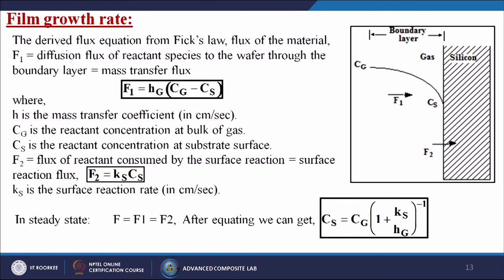So, the famous equation, calling it Fick's law, is F1 equal to Hg into (Cg minus Cs), where H is the mass transfer coefficient in centimeter per second, Cg is the reactant concentration at the bulk of the gas, Cs is the reactant concentration at the substrate surface. F2, the flux of reactant consumed by the surface reaction, is F2 equal to Ks into Cs, where Ks is the surface reaction rate in centimeter per second. In steady state, F equal to F1 equal to F2, after equating we get Cs equal to Cg into (1 plus Ks by Hg) to the power minus 1.